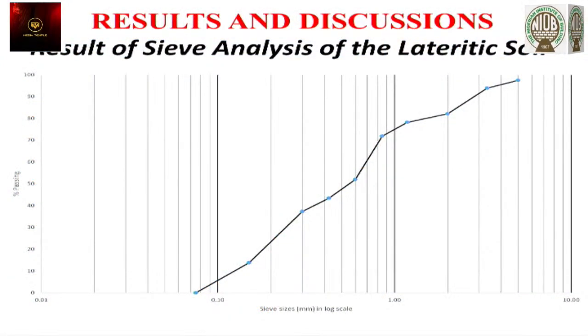Now, the sieve analysis of the lateritic soils that were obtained gave a percentage retained between 2.63 and 23.52%. And that is safe because it falls within the acceptable range of the Nigerian General Specification for Highway 2000, of not exceeding 35%.